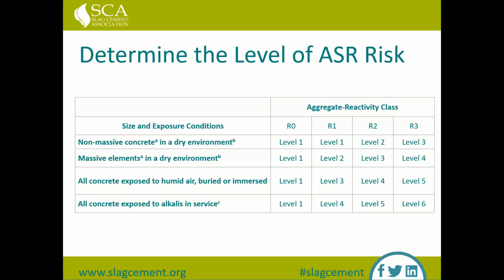The lowest level is associated with a non-massive concrete in a dry environment, giving very low risk of ASR. The risk increases if we now have a massive element in a dry environment, increases further if the concrete is exposed to moisture, and increases even further if the concrete is exposed to alkalis in service. Those alkalis in service may come from de-icing salts or from ocean water.